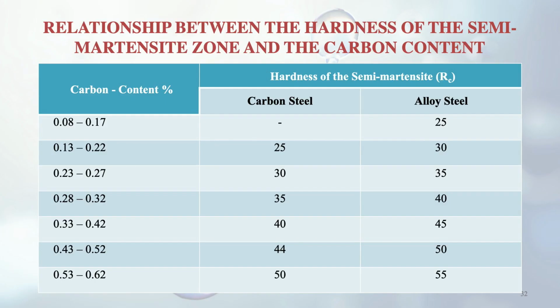So now we take up the relationship between the hardness of the semi-martensite zone and the carbon content. That's what I have discussed earlier also, the semi-martensite thing. So from here with different carbon content, you can see the hardness of the semi-martensite, meaning if 50% martensite is formed, what is the hardness? So suppose you have carbon content 0.23 to 0.27. In case of carbon steel, the Rockwell hardness number is 30, whereas in case of alloy steel it is 35. So this is the hardness of the semi-martensite. Similarly, we can see for other carbon contents from this table.